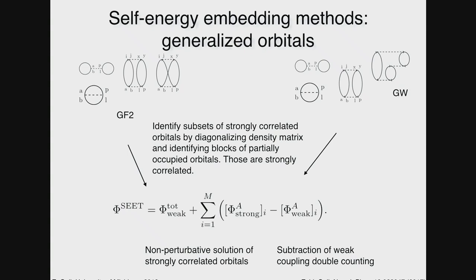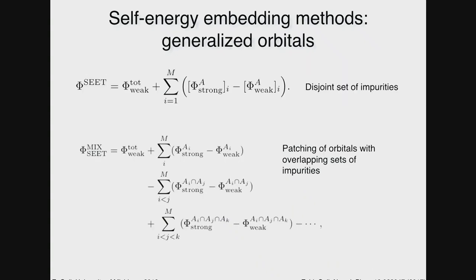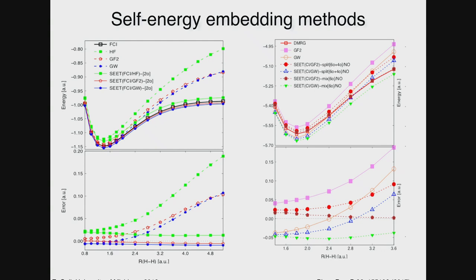Here's the math of how it actually works. The self-energy embedding phi functional is given by the weak coupling, or GF2, or GW phi functional in the entire space, to which you add a strong coupling solution in a subspace, and then subtract a double counting correction. And if we take this and we actually apply it to systems where we have exact solutions, like here, hydrogen molecules and chains of hydrogens, as a function of the stretching distance, we can see that as we're adding diagrams, as we make the correlated subspace bigger and bigger, we can actually become quantitative for the stretching of these molecules, not just in the weak coupling regime, but also as we pull these molecules apart.